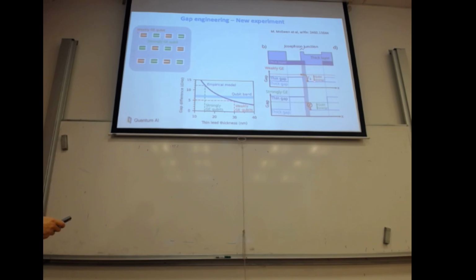So you have a profile like this, that is 2 Kelvin, 4 Kelvin, but the qubit that we have is around 6 and 8 gigahertz. So basically the qubit energy is higher than this profile. It means that if a quasi-particle arrives here, it can absorb energy from the qubit, and this qubit energy is enough to make it tunnel through. On the other hand, they also built strongly gap engineered qubits, and what they did is decrease the layer down to 15 nanometers, so that you have a gap that is 12 Kelvin. The energy of the qubit is not enough, if the quasi-particle comes cold, and we saw that they are cold, to cause the passage through the junction, and so the relaxation rate.